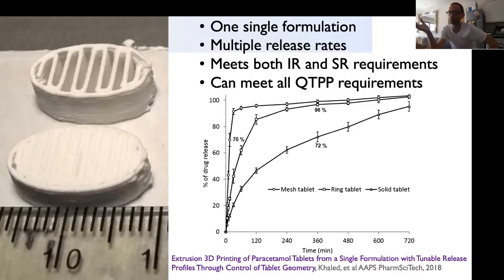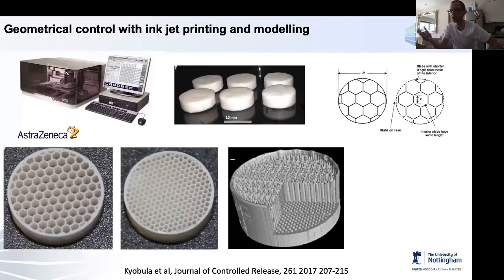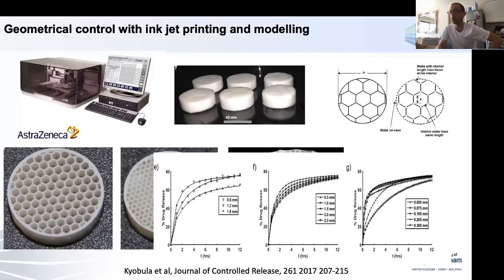And so here we worked with GSK to show that a single formulation could produce an instant release, which is with the mesh tablet, or a more sustained release, which is a solid tablet. And these met GSK requirements in their QTPP. So we're really confident that this could satisfy production requirements. We also did this with inkjet, and we backed that with modeling. Modeling was able to tell us what structures we should generate in order to be able to get instant release or sustained release.